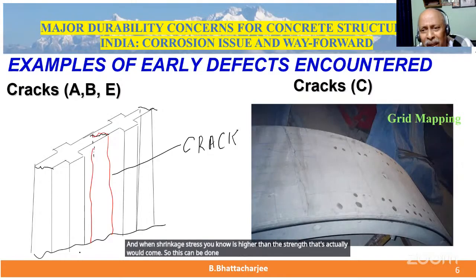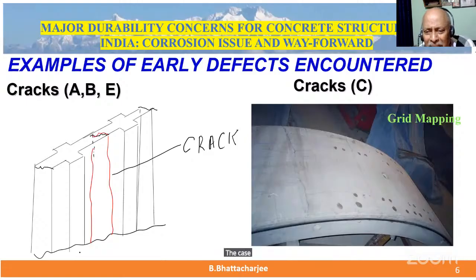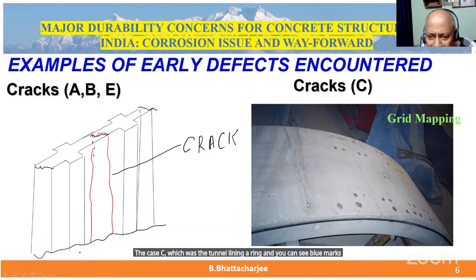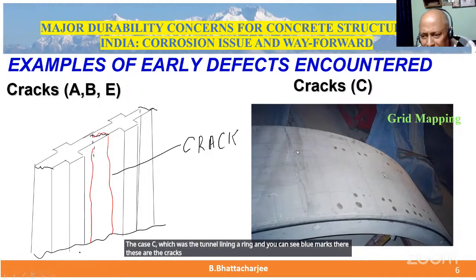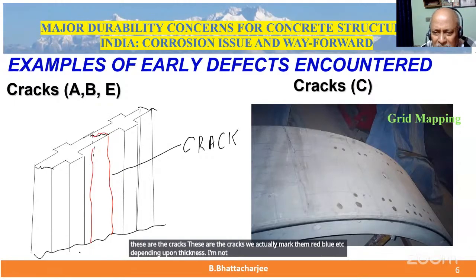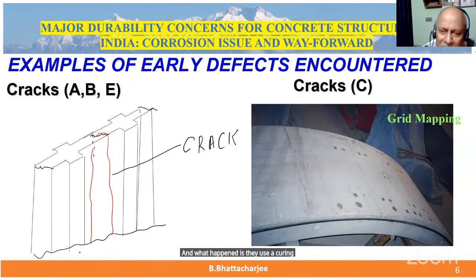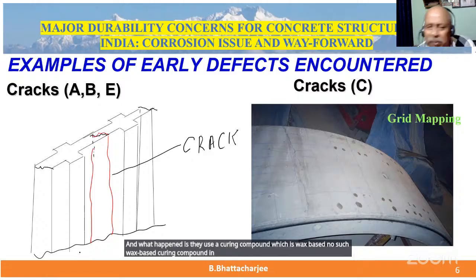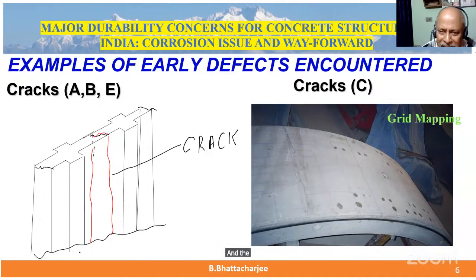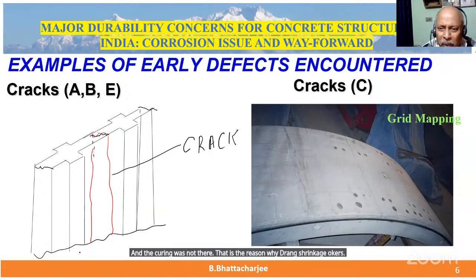This is for case C, which was the tunnel lining ring, and you can see blue marks there. These are the cracks. We actually mark them red, blue, etc., depending upon thickness. I'm not going to go into the details of this. This was thin. And what happened is they used a curing compound, which is wax-based. Now, such wax-based curing compound in India in the months of May and June on exposed concrete will simply melt. And the curing was not there. That is the reason, because drying shrinkage occurs often because of poor curing.